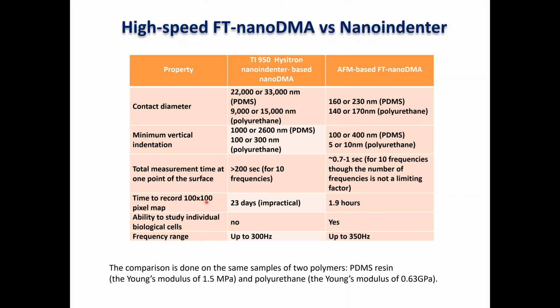In terms of time, just to give you a flavor, if you want to record a 100 by 100 pixel map, which is relatively modest, you need 23 days. It's completely impractical because of thermal drift. You'll get out of the range of your scanner pretty quickly. So from our experience, 12 hours, maybe 20 hours at max, but definitely not that much. With our AFM-based FT-nanoDMA, we have about 2 hours. And of course, we can get images of individual cells with that high resolution.